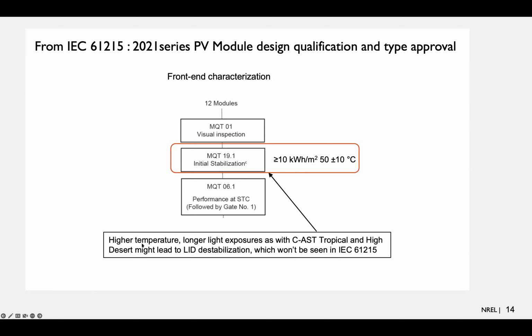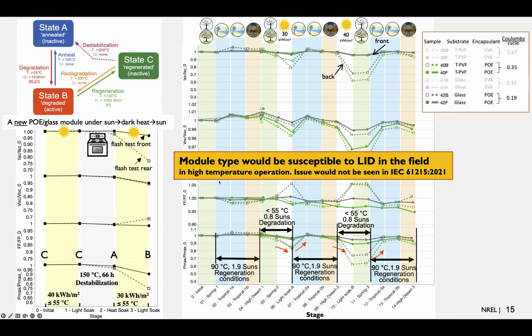But what we found is that higher temperature and longer light exposures, as with combined accelerated stress testing, tropical and high desert, might lead to LID destabilization, which won't be seen in IEC 61215. A module type that we tested here does just fine under a regular light soak, as shown there, but in combined accelerated stress testing, which replicates worst case conditions you can see in the field, you would in fact get light-induced degradation, and this is missed by IEC 61215.